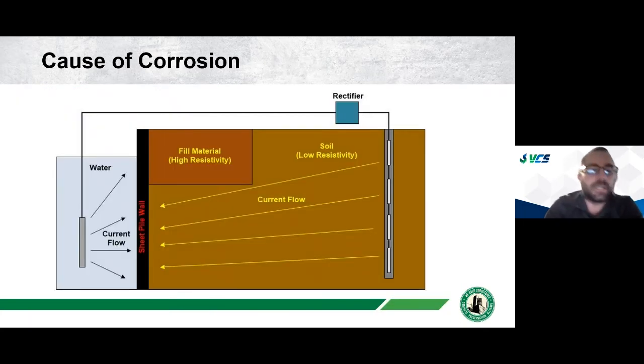And so what they had done is, during installation of the wharf, they had done the sheet pile wall, they had the native soil, but then to fill the gap from the wall to the native soil, they put in this kind of rocky fill, and it had a high resistivity. And so cathodic protection works on resistivity. So they had a water system and a soil system pushing current onto the wall.